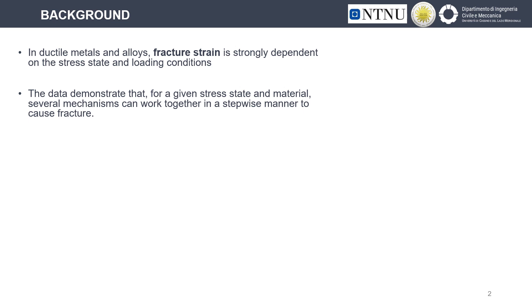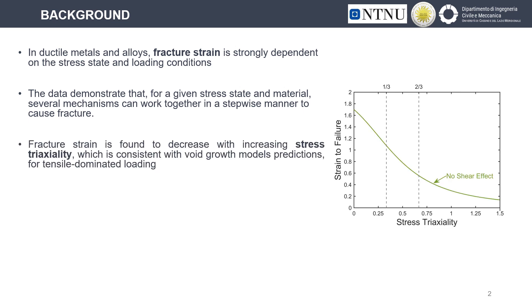It is well known that the fracture strain of a material — which is the final level of deformation the material reaches before fracture — is strongly influenced by the loading conditions, since different mechanisms can be activated and work together to cause the final failure. One of the first parameters introduced to address the influence of the stress state on material ductility is the stress triaxiality, which is the ratio between the applied pressure and the equivalent stress. Consistently with void growth model predictions, it was shown that increasing stress triaxiality leads to a reduction in ductility.